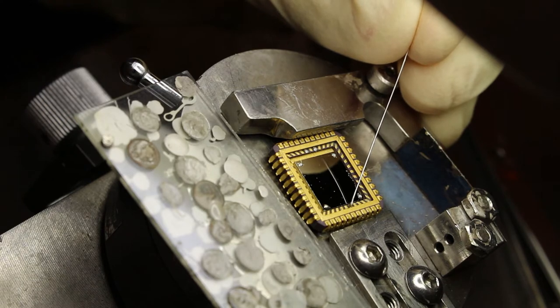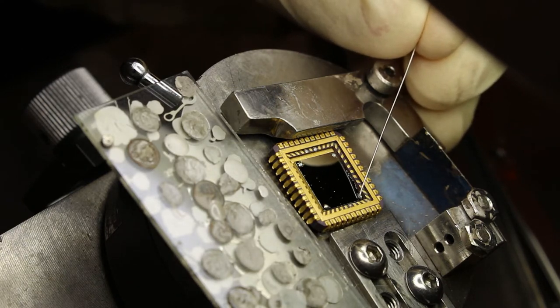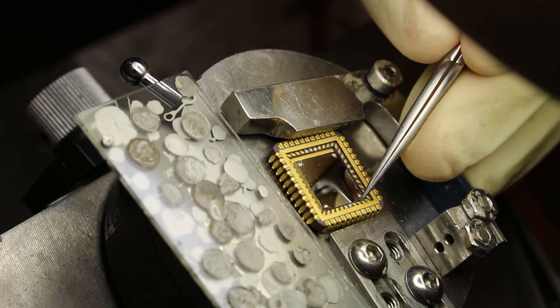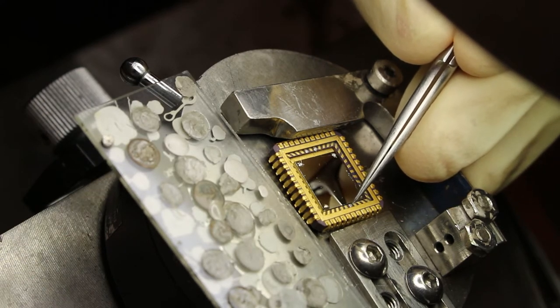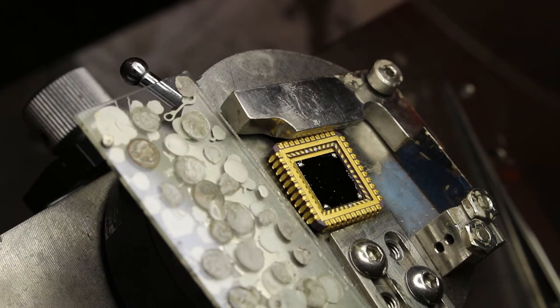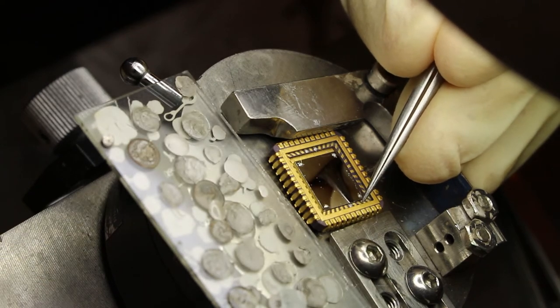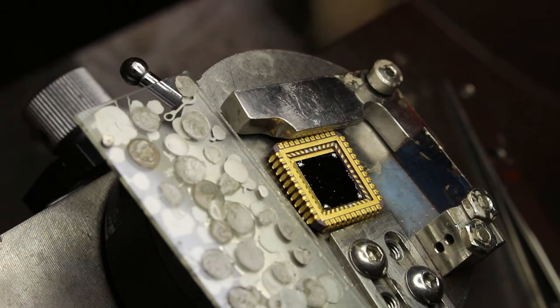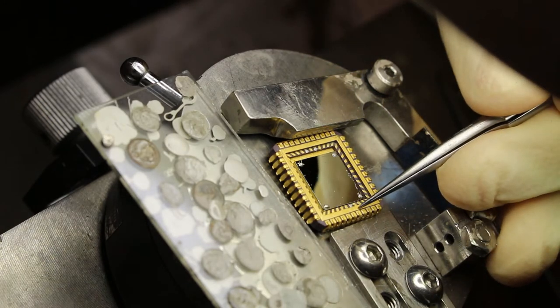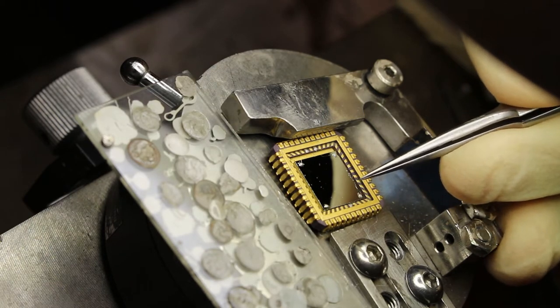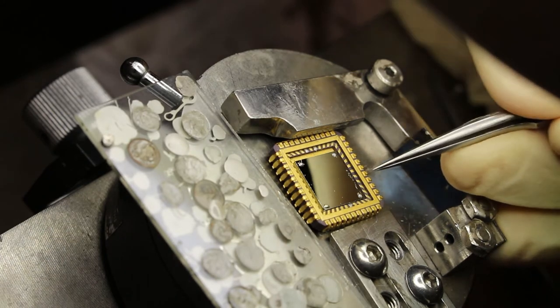Then you just touch it to the wire, both on the indium to make sure that the wire is making good contact, and on the contact pad. It's important to make sure that the silver paint doesn't contact the ground planes. So that's up here, and that the silver paint doesn't run down over the edge and go inside to the ground plane on the bottom. So you need to get it just on the pad that you want.